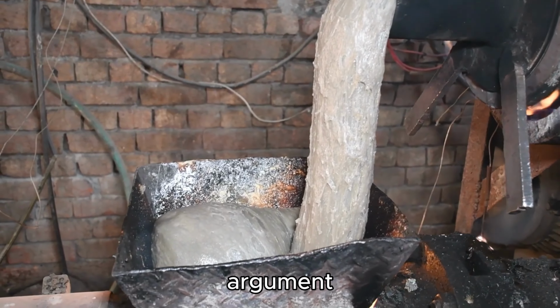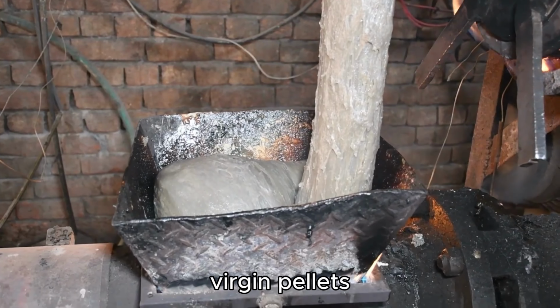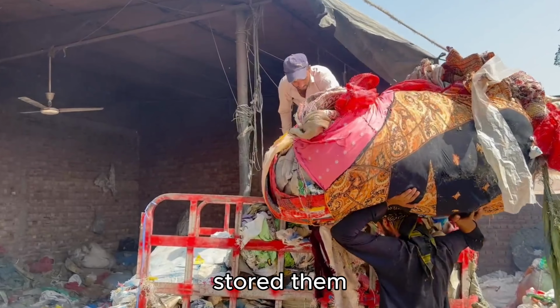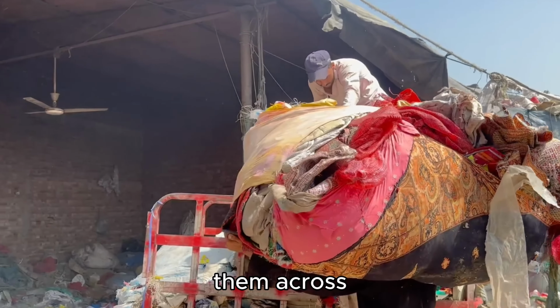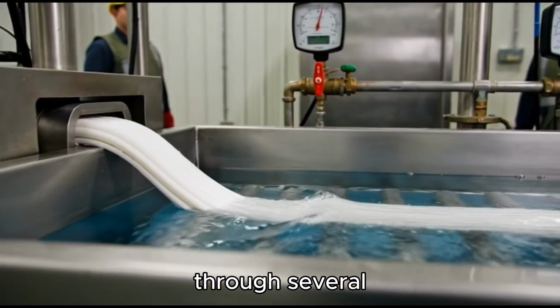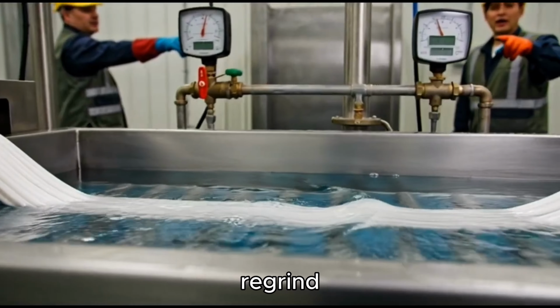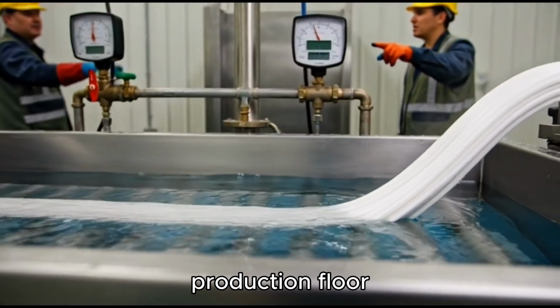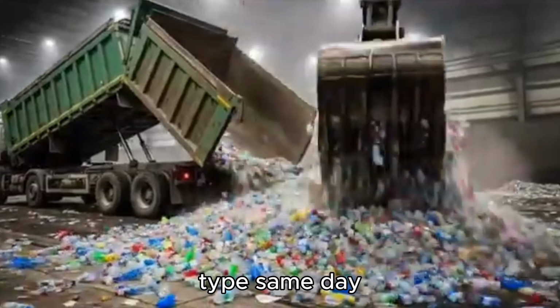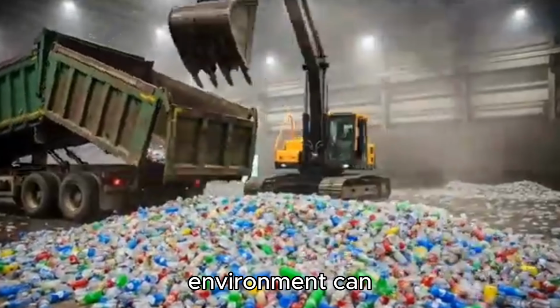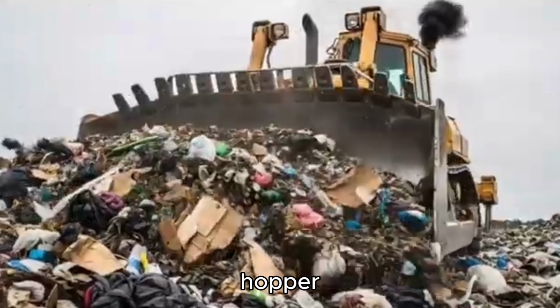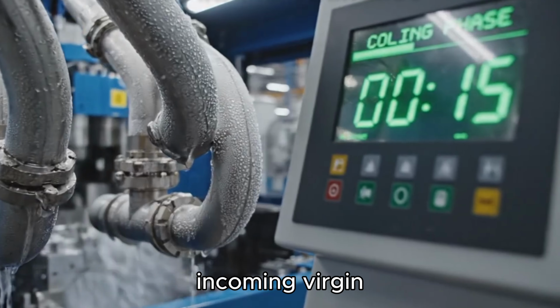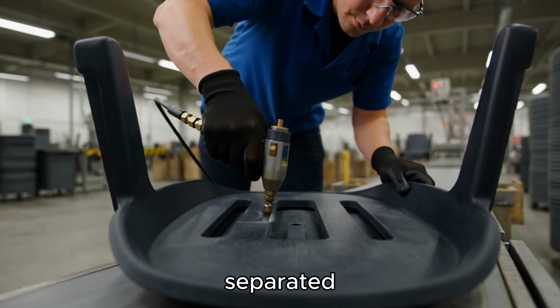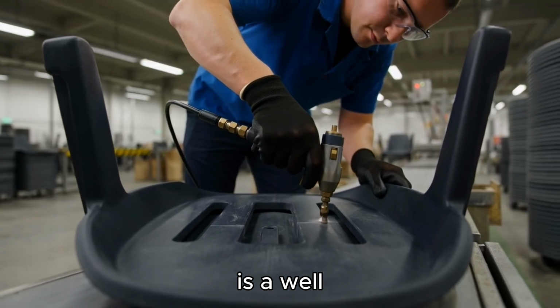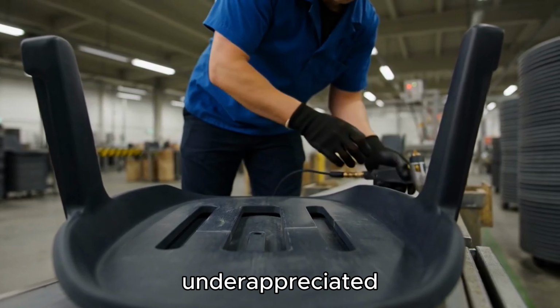There's also the contamination argument running in the opposite direction. Virgin pellets arrive from a supplier who may have stored them in a warehouse for months, shipped them across multiple states, and handled them through several transfer points. In-process regrind collected directly from a granulator on the production floor, same material type, same day, controlled environment, can actually arrive at the blending hopper in cleaner condition than some incoming virgin feedstock. As long as material types are kept strictly separated, in-process regrind is a well understood and often underappreciated input.